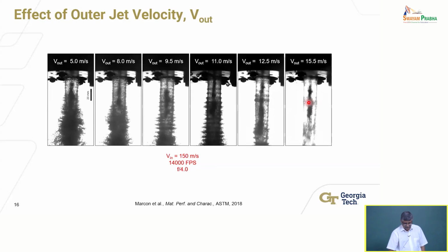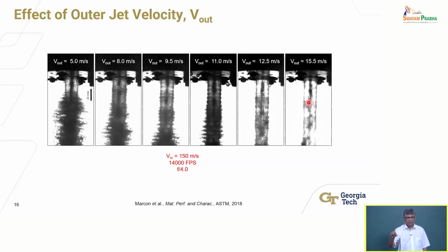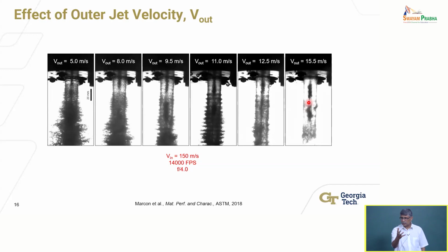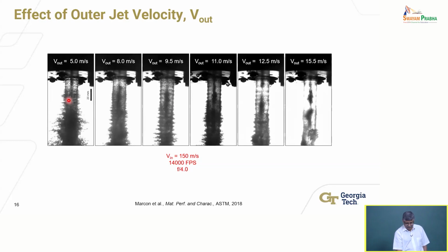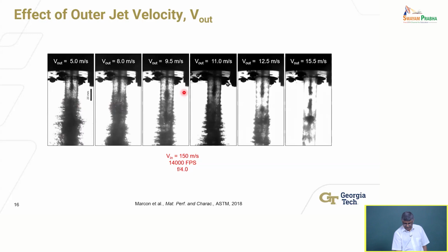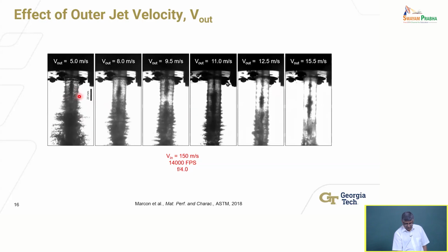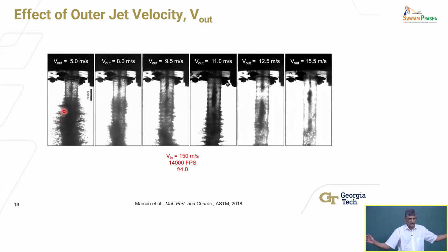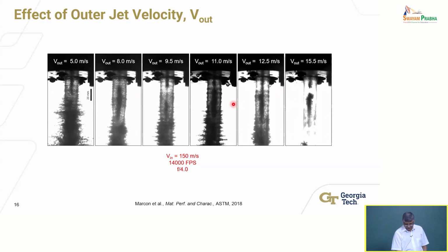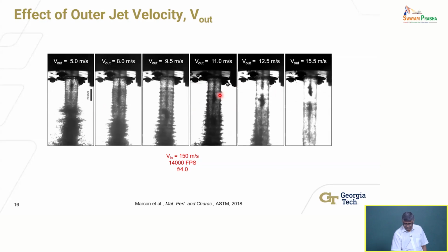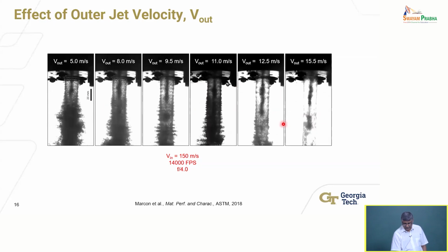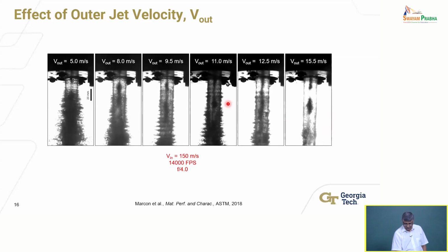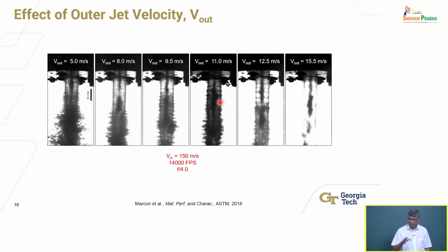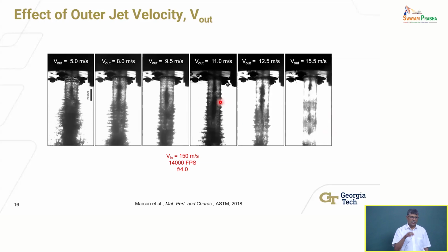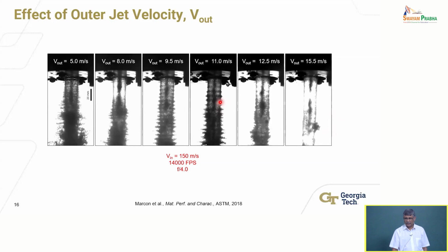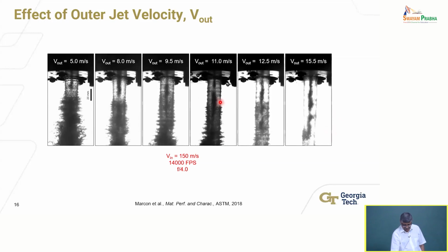What happens when I keep the inner jet velocity fixed at 150, because 150 gave me the highest, right? Largest cloud, what looks visually to me like the strongest cloud. I vary the outer jet velocity. And you can see here that, at very low velocities, it's problematic. You completely destroy the flow and it essentially dissipates. And it improves a bit, and then at about 11 is where we picked the best case. After that, you can see, it's okay. You can do this as well at 15 if you'd like, but you generate the strongest cavitation clouds at a combination of 150 meters per second inner jet velocity and 11 meters per second for the outer flow. Okay, so that's our optimum. Okay, in our case, right, for our design.